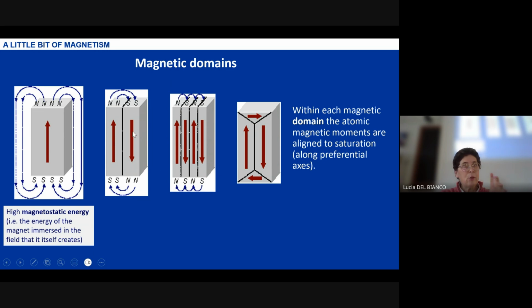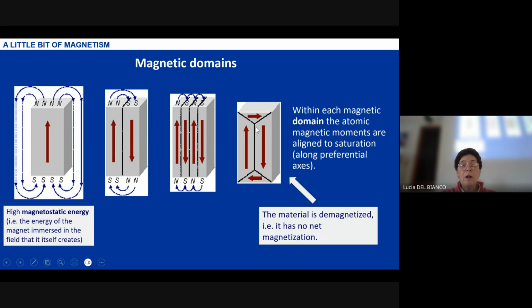And in each domain, the magnetization is the saturation magnetization. But the orientation of the magnetization changes from one domain to the other. And therefore, in the most favorable situation, the material is able to completely close the flux, one says, so to completely annihilate the presence of this external field, so reduce to zero the magnetostatic energy, but the material is no more magnetized. The material is demagnetized. It has no net magnetization. And the direction of the magnetization in each domain is along a preferential spatial direction. This is an important point.